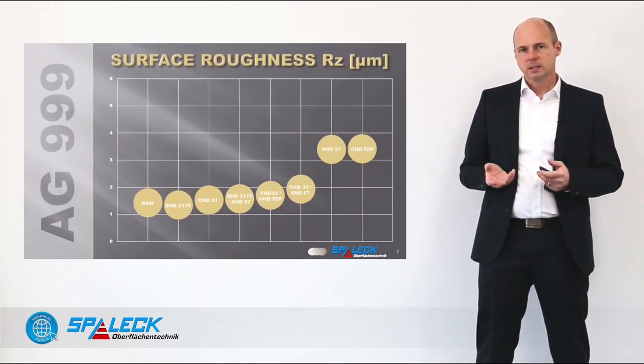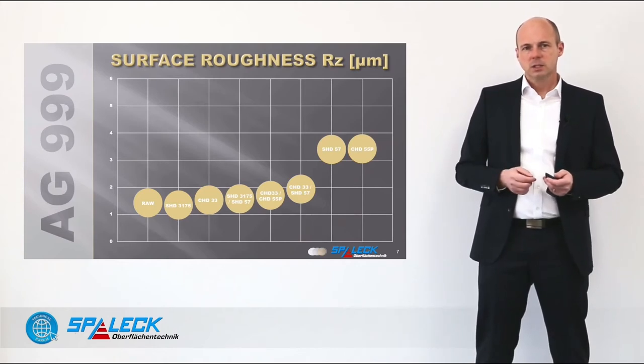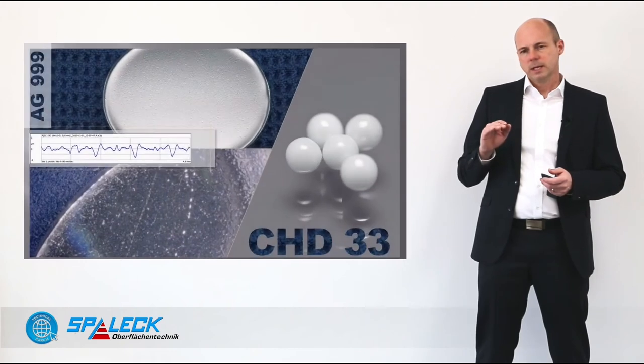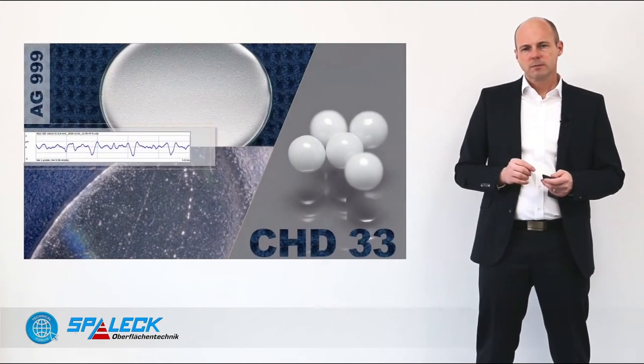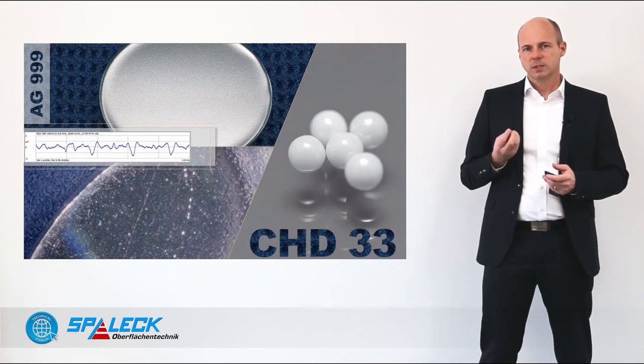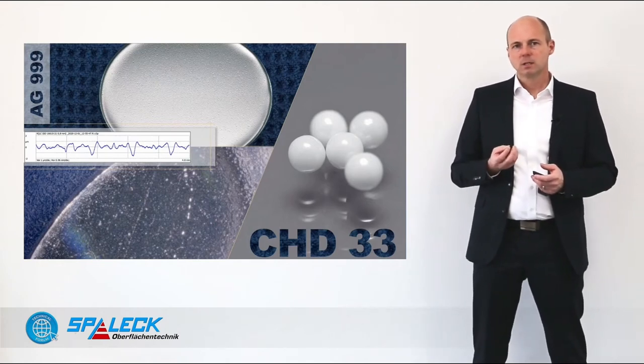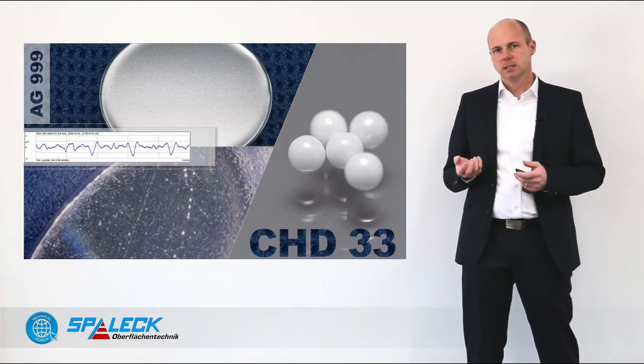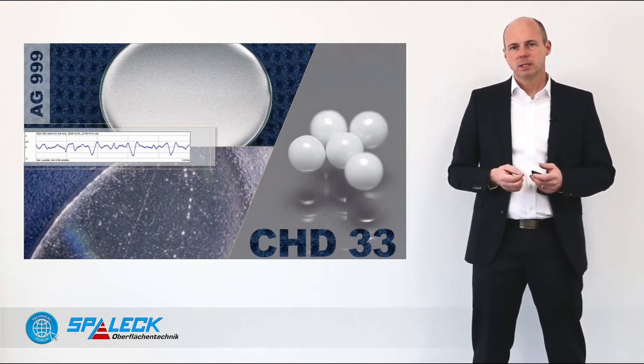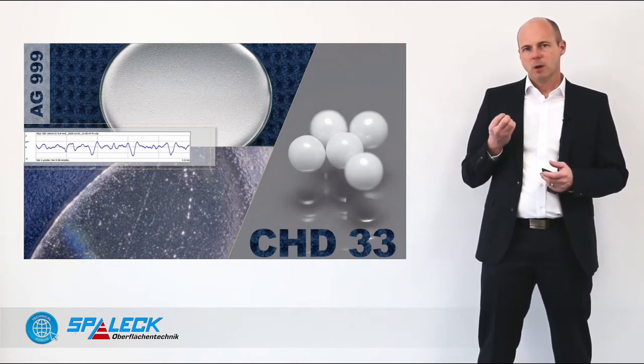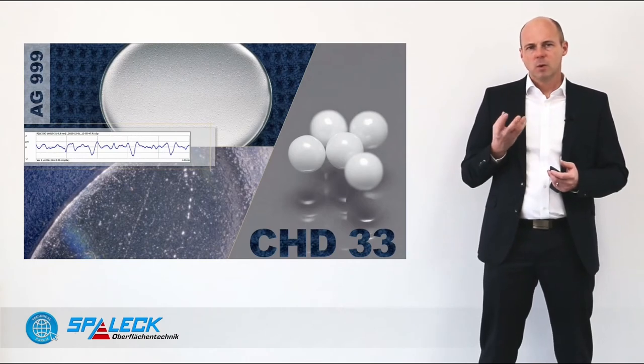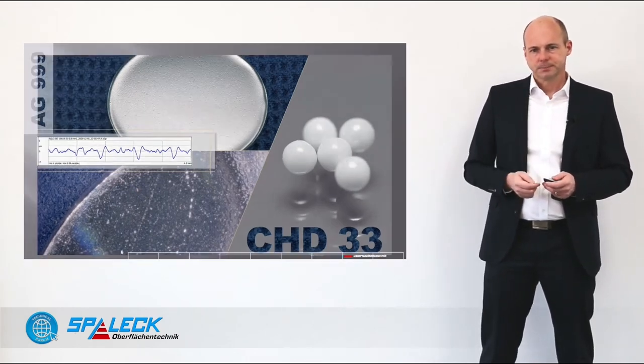If you compare this to the CHD, the ceramic media, you get a similar surface roughness, but because the CHD balls are 20% lighter, about 4 kg per liter instead of stainless steel at 5 kg per liter, you generate a bit brighter, shinier surface.